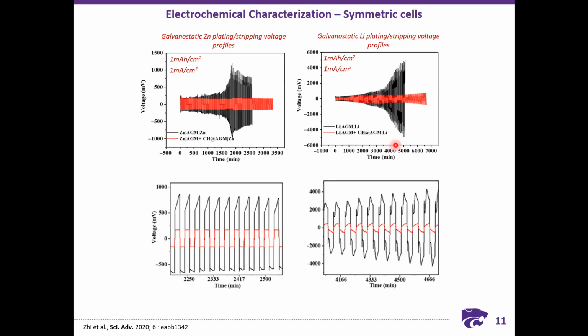Similar behavior is seen in the case of lithium symmetric cells as well. In these zoomed in figures, you can clearly see that with the use of interlayers, the stripping plating overpotential is very minimal, almost less than half of what can be achieved with the use of AGM separators without any regulation of flow of metal ions.